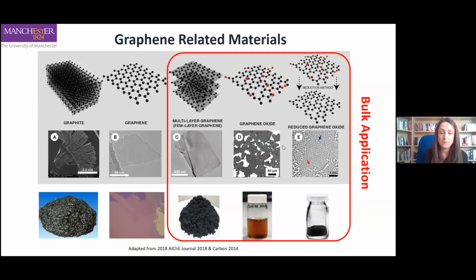The next image along here shows graphene oxide, and this is the most common functionalized form of graphene, and you'll hear about it a lot. Some of the carbon atoms here are functionalized with oxygen containing groups, so carboxyls, hydroxyls, epoxy groups. And there's quite a few reasons why you'd want to use graphene oxide over graphene. Firstly, it's quite straightforward to make. It's an easy chemical route, and what you get when you produce graphene oxide is a stable aqueous dispersion, and that's because with all the groups on it, graphene oxide is far more hydrophilic than graphene. It's then very useful to have that in dispersion form to dose into other systems. Although with that functionalization, it does come at the expense of some other properties, say electrical properties of the graphene. Also, because it's got these functional groups, it's got more bonding sites. So sometimes you want to use GO instead of graphene because it's more compatible with organic systems, so polymer systems, for example.